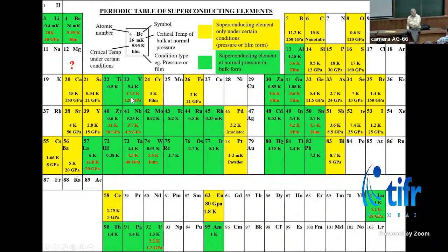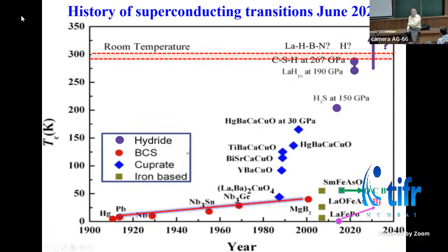Once the mercury started, this graph we might have seen from many people, including theoreticians, shows these things, though theoreticians didn't contribute much to this. But the point here is that superconductivity is everywhere. The green ones are at ambient pressure. The shaded ones are either in thin films or under high pressure. Even things like iron and chromium, which are supposed to be magnetic, are superconductors. The biggest hole is in bismuth, because bismuth was superconducting only under pressure before. It could go up to a very high temperature for those days, about 7.2 K. I'll come back to this slide a little later. So I think superconductivity picked up. Now you see it all over YouTube and so on.